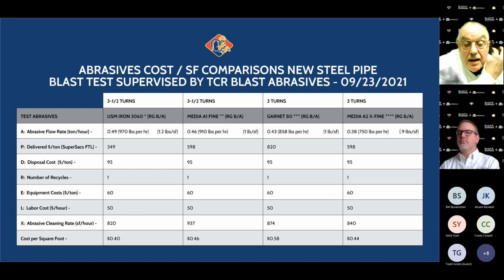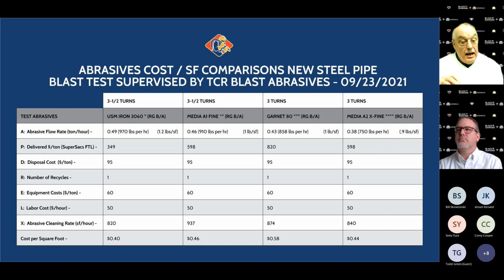It was less than the other 2, but again, we turned it down a little bit, the micro valve, so it's going to have less media coming out. So it's at 0.43 tons, and the A2, the extra fine media, was at 0.38. So it was the least. And then the cost per ton, this is average cost based on relatively current freight rates, $349 a ton versus the steel slag material was $598, garnet at $820. This is all per ton delivered, full truckload, and then $598 as well on the extra fine.